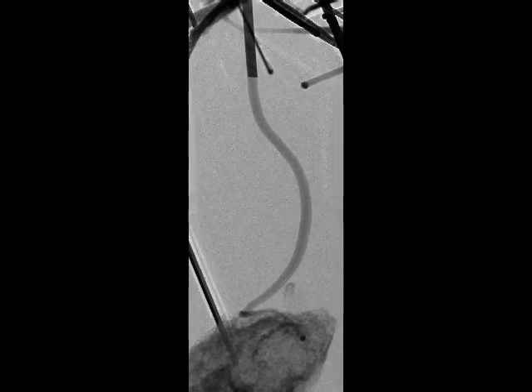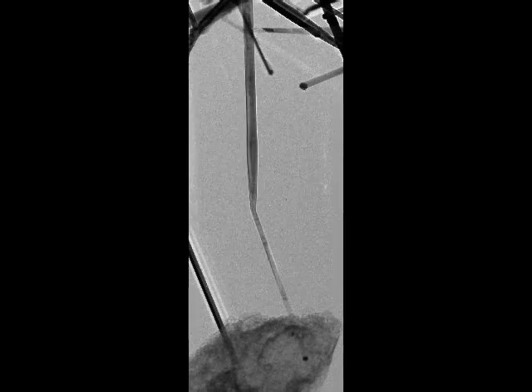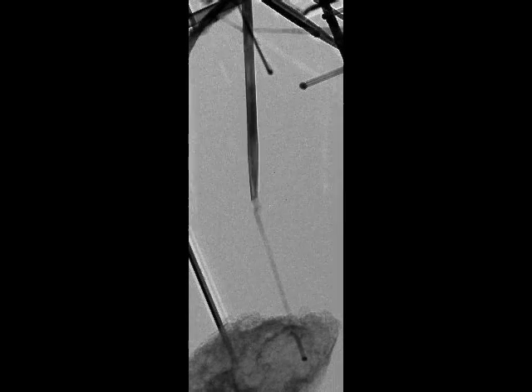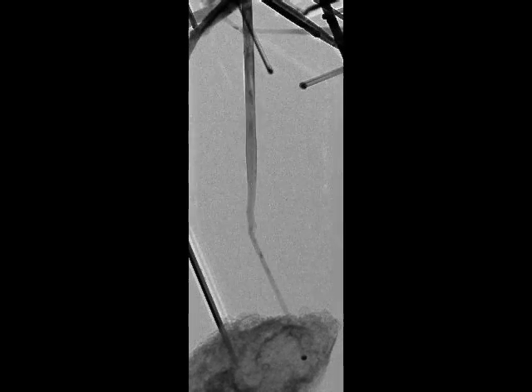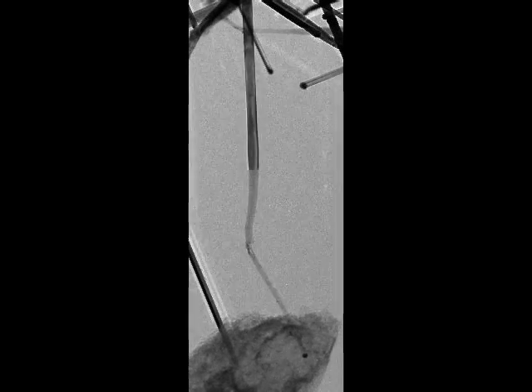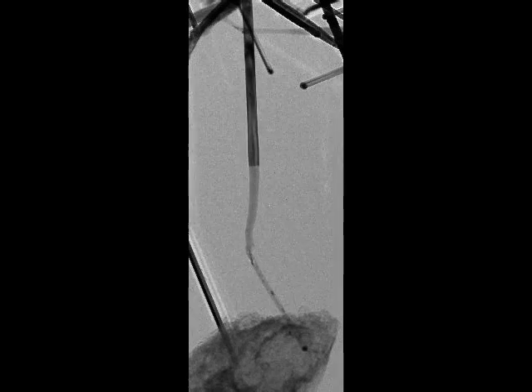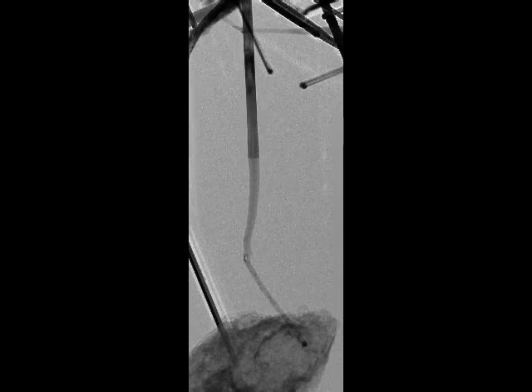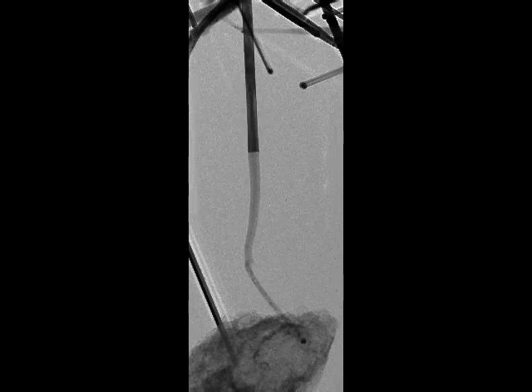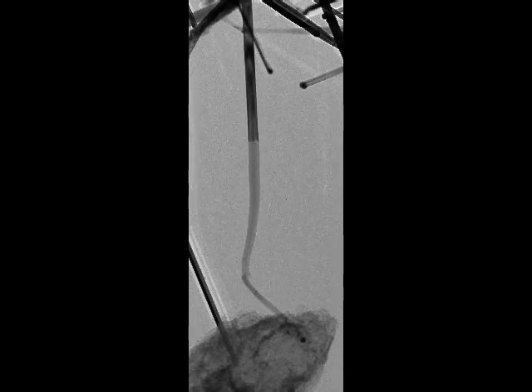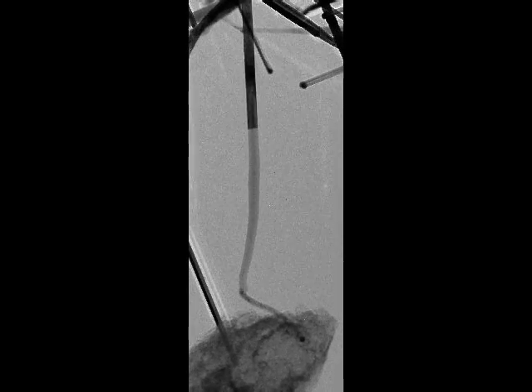The lighter contrast eats one atomic layer by one atomic layer into the crystalline germanium core of the wire. And the expansion in this case happens axially along the length of the wire, as opposed to radially, which we have just seen for the case of germanium.